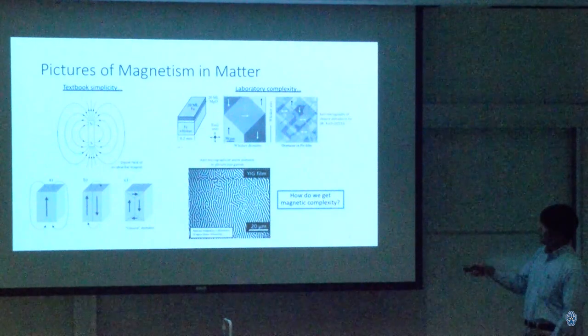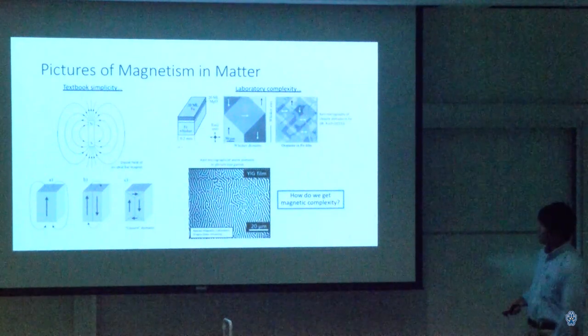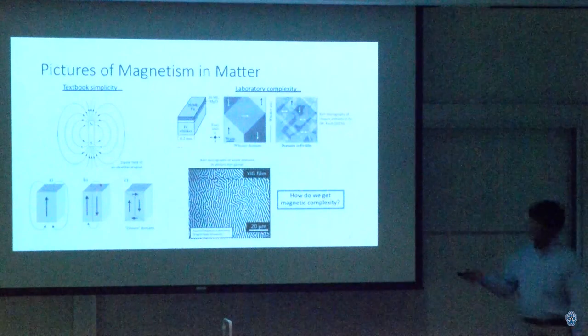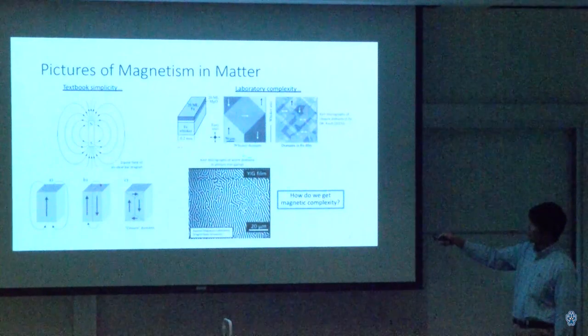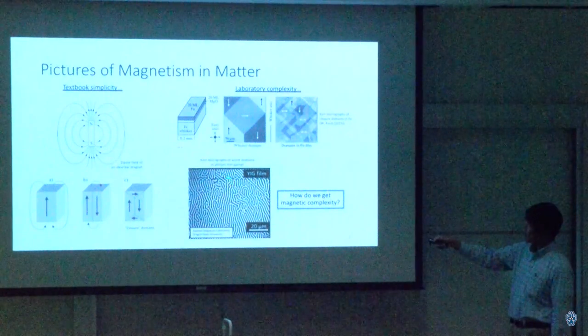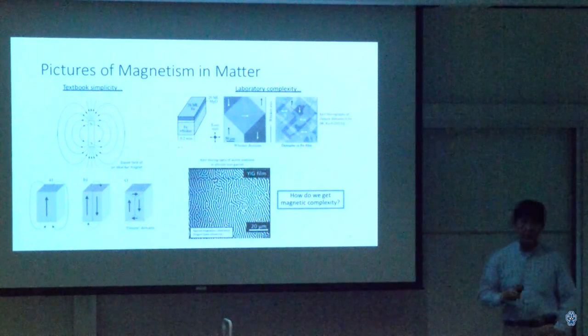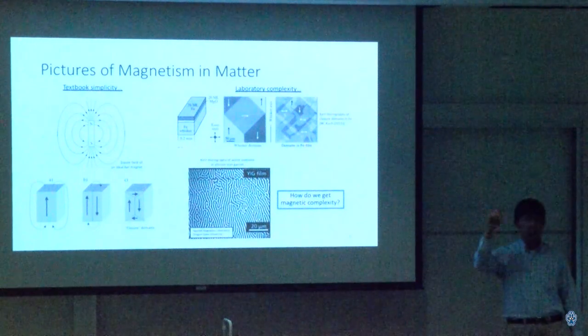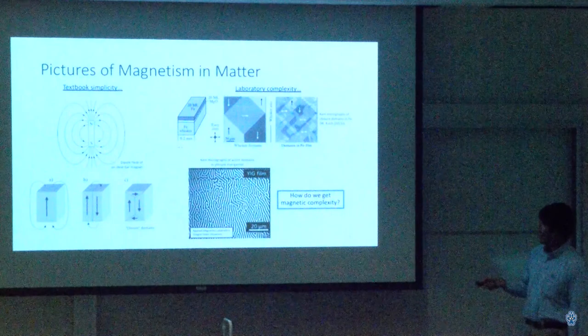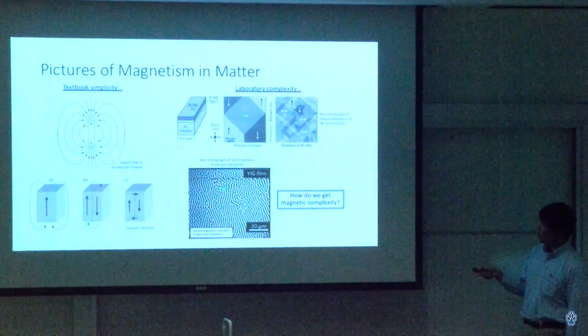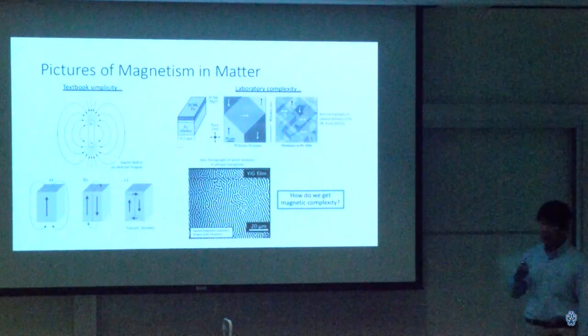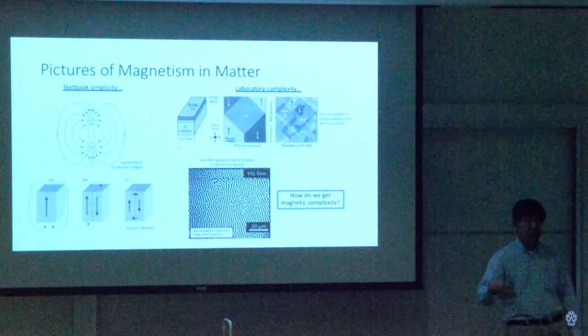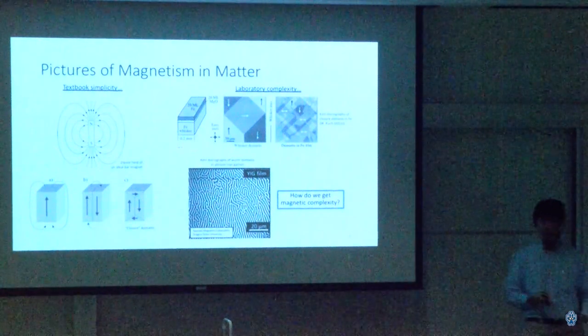If you take another iron-containing material, yttrium iron garnet, the picture is even more complicated. It's still a Kerr microscope image, but in this case, the black and white indicates whether or not the local magnetic moment points up or down. But instead of having patches, you have linear magnetic domain structures that wander about. It's reminiscent of worms, hence the term worm domain.